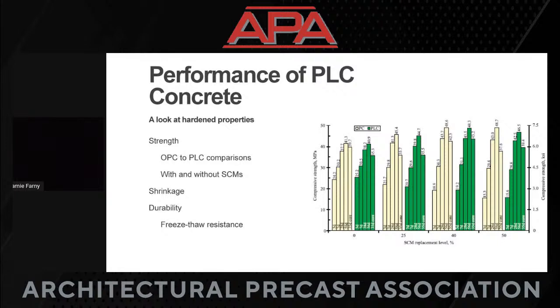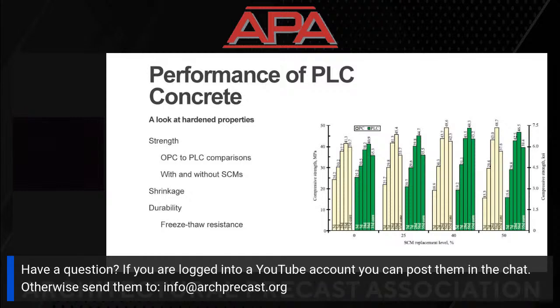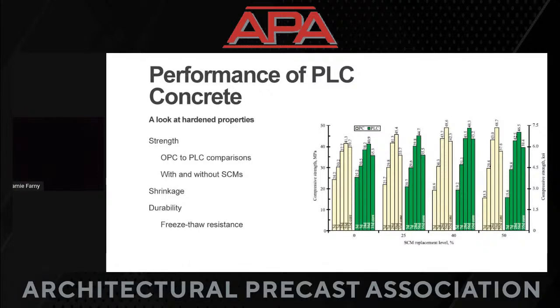We can talk about the performance of PLC concrete, those hardened properties. This figure at the right is a very important figure. It has pairs of graphs that look at, in the yellow or tan mixtures, bars, these versus the green ones, for 0, 25, 40, and 50% SCM replacement levels. So these have no SCMs at the left. These have only 50% PLC or Portland cement with a 50% SCM blend in them. And we look at the strength from 3 to 7 to 28, 35, all the way out to, we even take a core at a year. And you can see within each set of graphs that the green and yellow, tan, are almost identical overlays of each other.